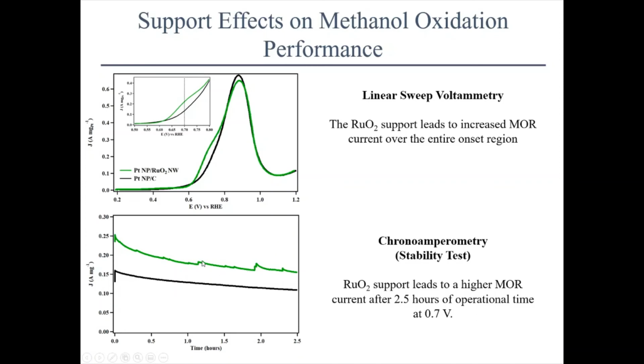And if you looked at the electrode during this 2.5 hour window, you could actually see carbon dioxide bubbles forming. And that's why we got these little sawtooth patterns. As a bubble would pop off, the activity would go back up. So the suppression of the activity here was in part due to the formation of carbon dioxide bubbles. In the other case, we did not see that sawtooth pattern, and we did not see observable carbon dioxide formation with the carbon-supported particles.